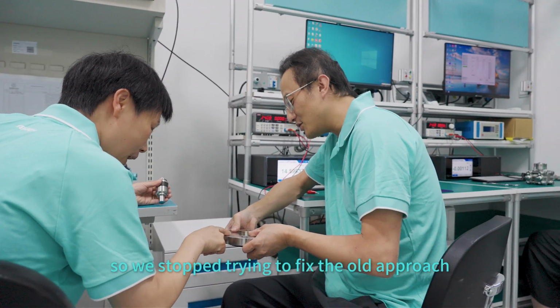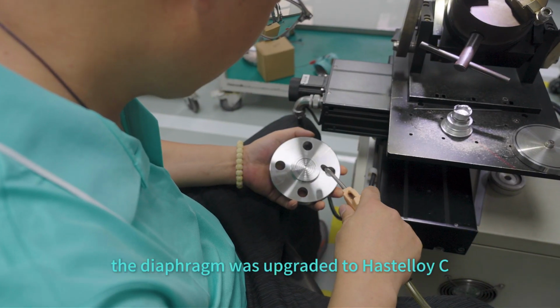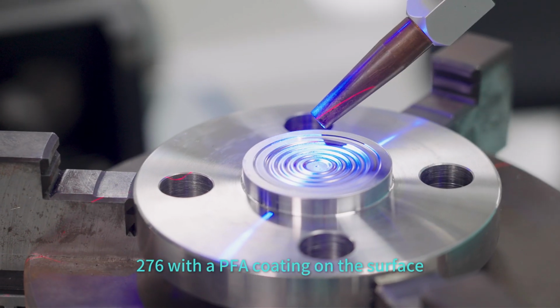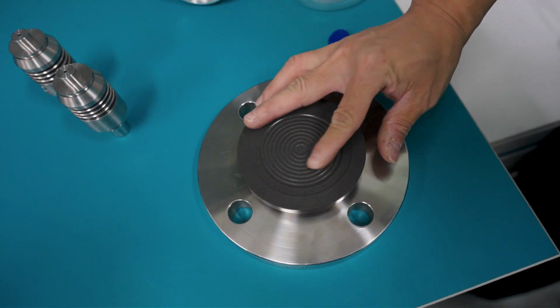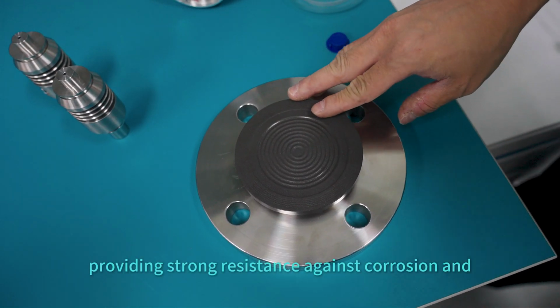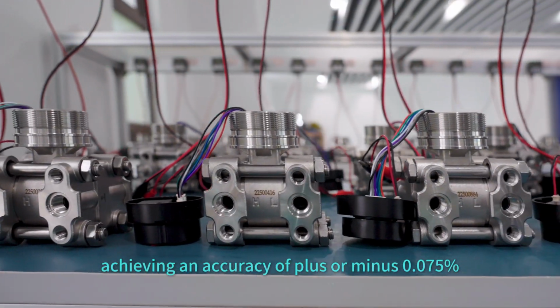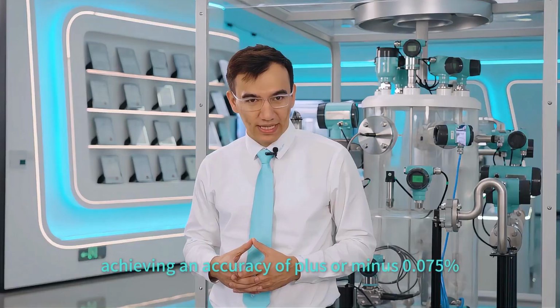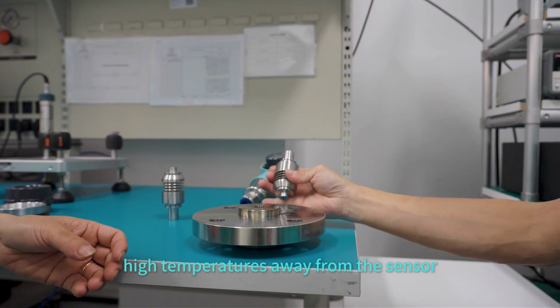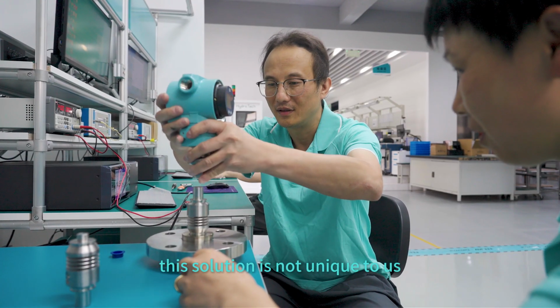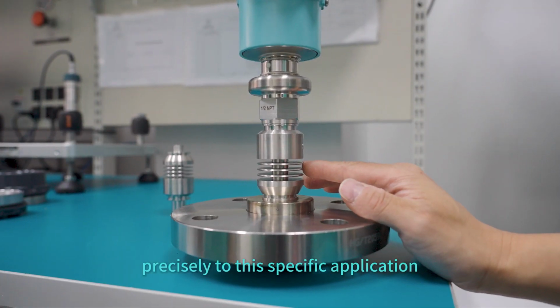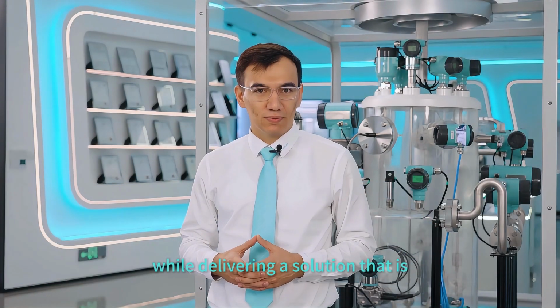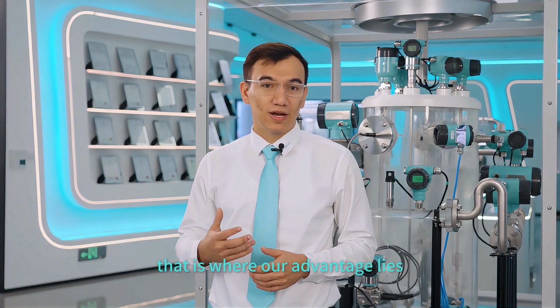So we stopped trying to fix the old approach and took a completely different path. The diaphragm was upgraded to Hastelloy C-276 with a PFA coating on the surface, providing strong resistance against corrosion and preventing deformation even under negative pressure. The sensing core was replaced with single crystal silicon technology, achieving an accuracy of plus or minus 0.075%. Between the diaphragm and the flange, we added a 60 mm heatsink to keep high temperatures away from the sensor. This solution is not unique to us, but applying the right technology precisely to this specific application, while delivering a solution that is both reliable and cost-effective, that is where our advantage lies.